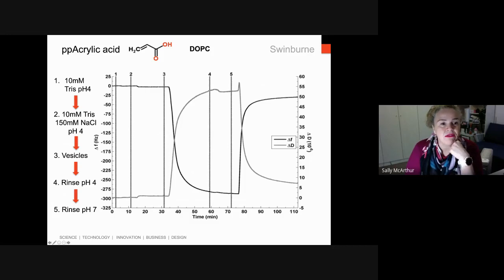And then at point 3, we introduce the vesicles, and suddenly we're getting a very large adsorption of vesicles directly onto this acrylic acid surface at pH 4. And at the same time, the dissipation component rises massively as well. So that tells us that we have adsorbed a layer of intact vesicles directly onto our surface. So it's now like a layer of jelly sitting on top of our plasma polymer.